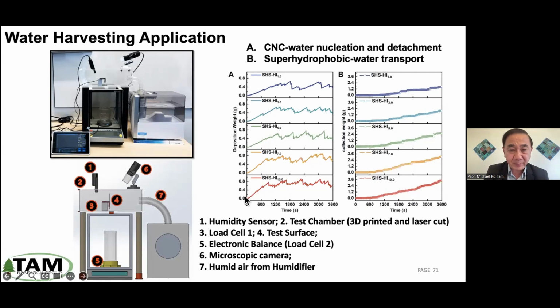As you can see, when the amount of water collected reaches a point, then it cycles, right? It drops off, increases, cycles. So this is the indication of detachment and reformation of the water droplet. And at the bottom, number 5 is the total amount of water collected over a certain amount of time.